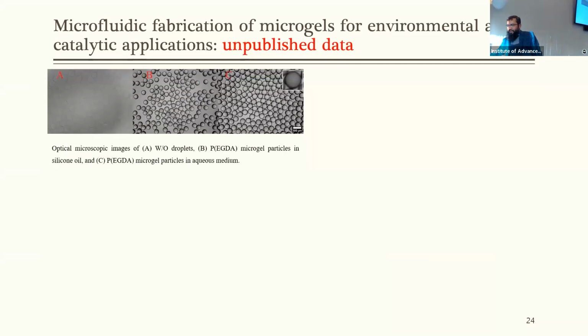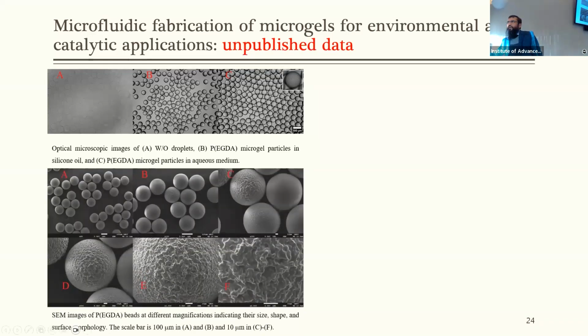As a proof, I am going to show some unpublished data just to describe that we were successful in addressing both problems. For example, we have obtained a highly monodispersed microgel system with a coefficient of variance equal to 1.16%. You can see the particles formed by the microfluidic fabrication method are highly uniform in size. They have very low polydispersity. The particle size is much larger than the particles fabricated by free radical precipitation polymerization, in the few hundred micrometer range.